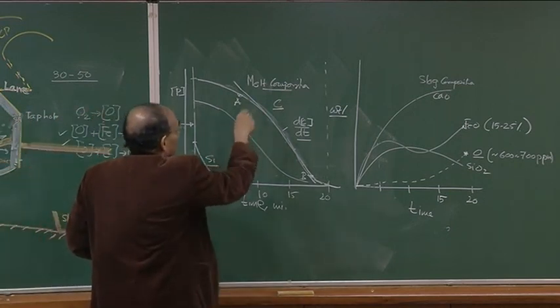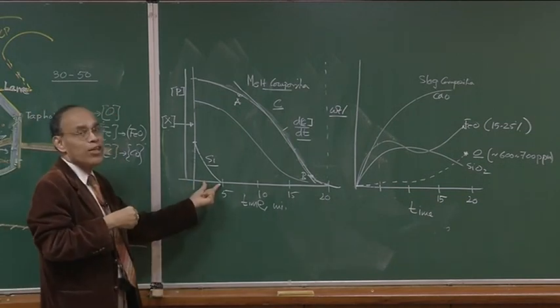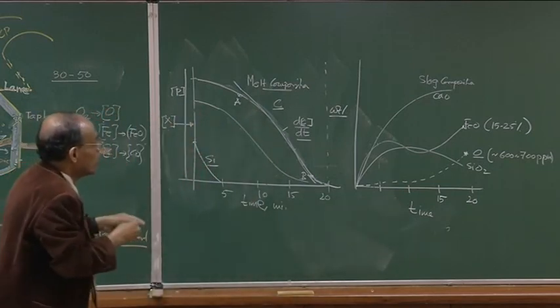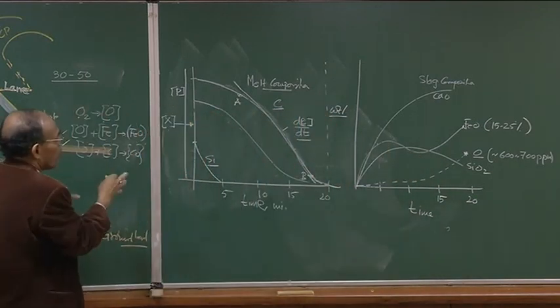Silicon is clear, and try to visualize the thermodynamics of the reactions that I discussed when I was talking about the principles of steelmaking. In the first 3 minutes, silicon has great affinity towards oxygen and gets oxidized, and phosphorus removal becomes very rapid, particularly during this period, because now you have a very basic slag. From here to here, you are talking about a large amount of lime, and carbon is also removed quite a bit. There is not much reducing atmosphere, there is some FeO in the slag itself, the oxidizing power is good, and conditions are favorable.